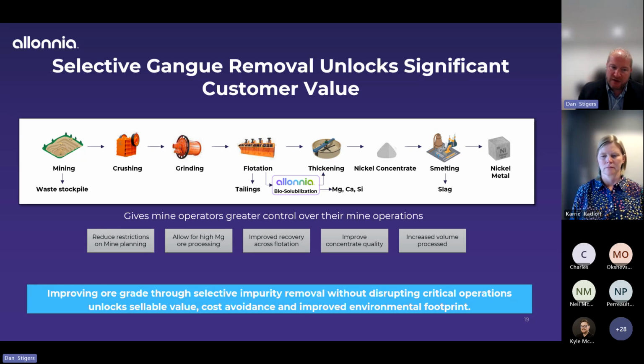And so what we see is with a single step, essentially, we're able to drive increased value with the generation of higher throughput or lower costs with regards to making your ton of metal, a pathway to lower CO2 emissions on the plant, and to reduce the amount of tails that you generate, all in the same separation step, with, as we envision, a relatively small footprint, because as you noted in Karrie's data, the amount of material we're able to remove is significant, and you don't need to necessarily remove all the magnesium from your nickel stream. But if you're able to remove a portion of it very efficiently, you can control the final targets of what it is you're generating in the concentrate.